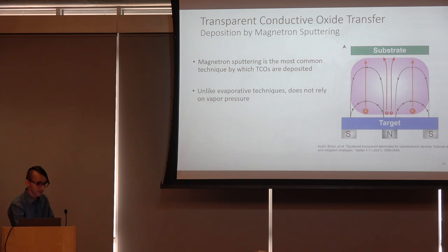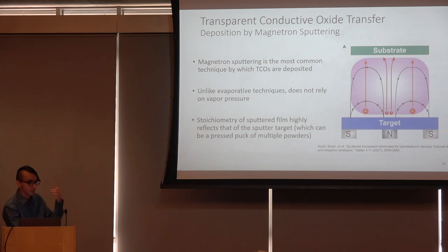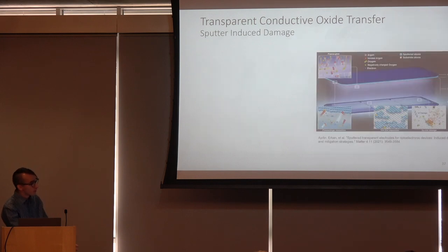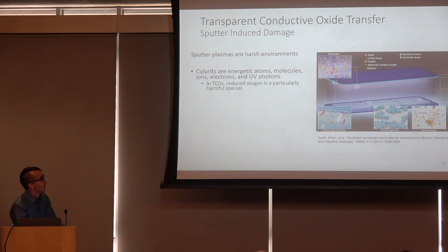Unlike evaporative techniques, this doesn't rely on vapor pressure at all. And so you can have a high degree of fidelity in stoichiometry between your sputtered film and your sputter target. Unfortunately, this process is also quite aggressive. Plasmas are harsh environments, as probably comes to no surprise.